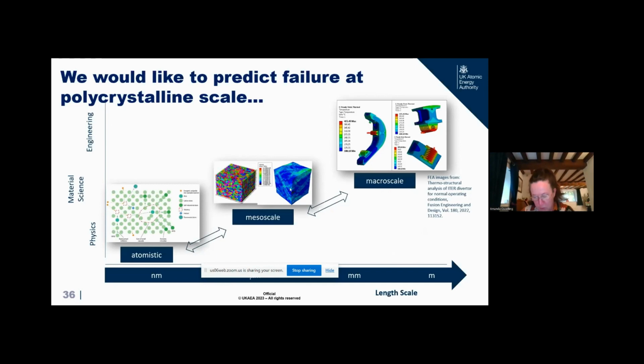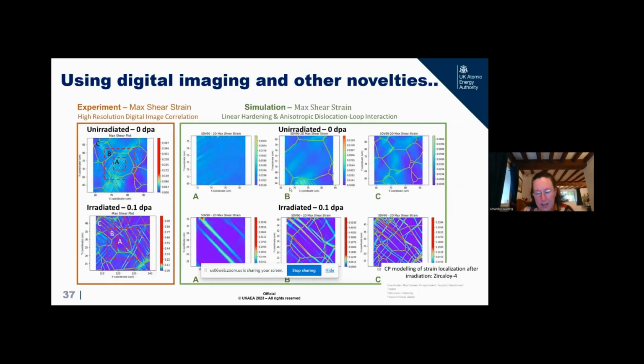And so this is the modeling we're trying to do using some very clever ideas from academia, but also from industry. We are taking materials at polygranular level. So you're seeing multiple grains in this image, and we're irradiating them with small levels of damage over here. And we see typical phenomena of slip bands being created in the material. And we are able to pick that up in real life using digital image correlation, where we actually at high resolution pick up the pictures under the microscope. And then we're emulating unirradiated and irradiated using our simulations, so digital space. And we're getting, I think, pretty good replication.